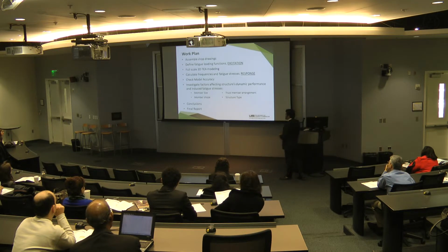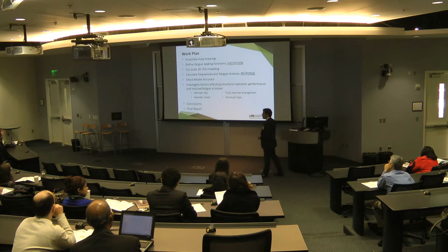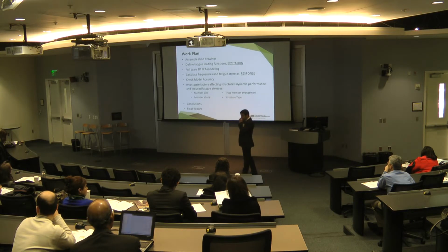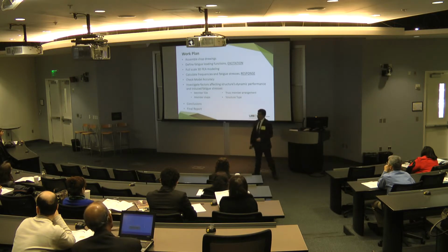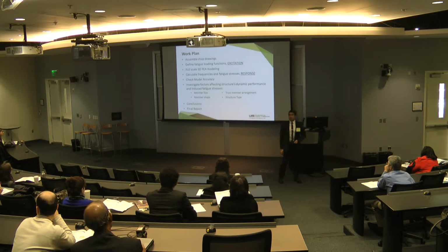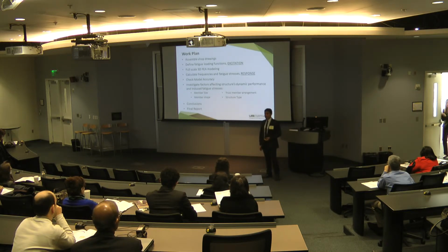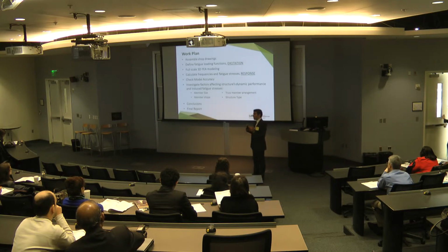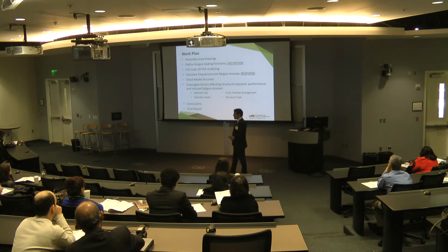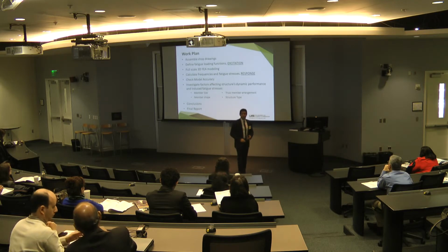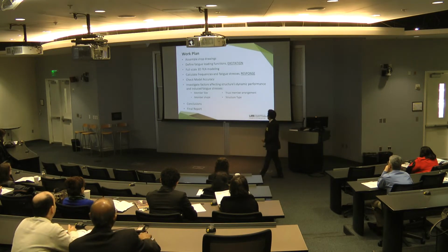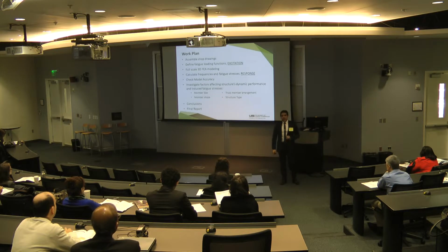Then, a full-scale 3D modeling has been performed on a finite element analysis software. I used SAP 2000. From this analysis, I calculated the frequencies of the structure. And for checking its accuracy, I compared it with experimental field data. I modeled one structure that has already been in the field, then made some modification to the structure so that the eventual frequency will match the frequency of the model. Then I got its responses, which was represented in fatigue forces at critical sections of the structures.